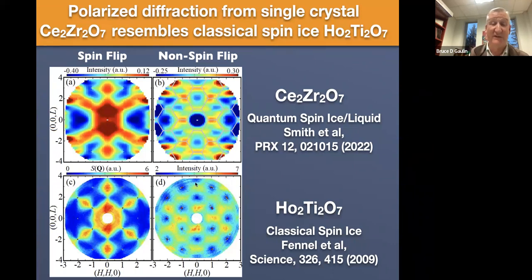And so it's not surprising that you would have the signature of interactions beyond near neighbors in this zone boundary scattering. What is surprising is that we see the same thing in cerium zirconate. Dipolar interactions are going to be a factor of 64 times weaker in cerium zirconate compared to holmium titanate, but somehow we see the same zone boundary scattering. Anyway, you can see there's interesting similarities and differences between these polarized diffraction patterns in the two cases.